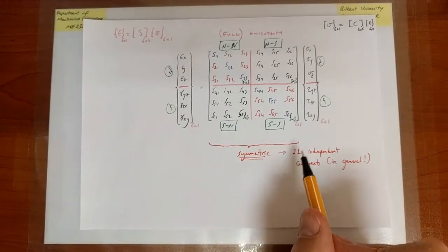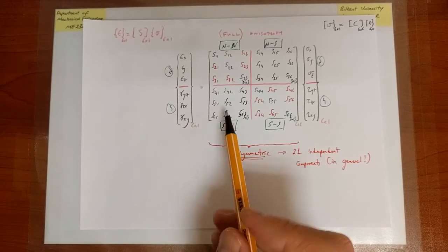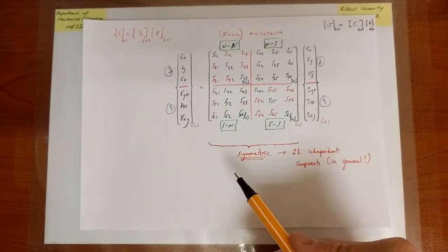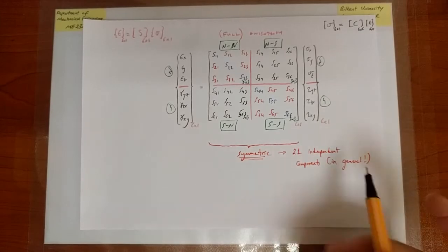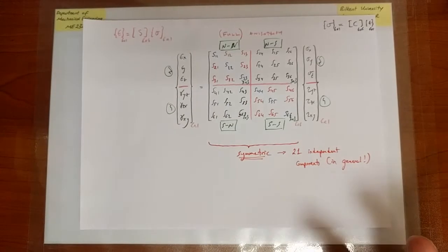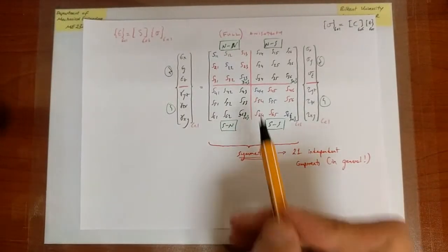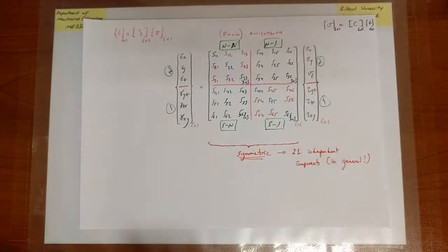So you have to go ahead and do experiments, determine the full form of this compliance matrix, and then looking at its structure, you can deduce whether it fits into some special form of anisotropy or it is in its full generality, or perhaps you're lucky and it comes out to be isotropic, okay? But that you recognize by looking at the form of the compliance matrix, which will have 21 independent components, okay? All right, good.